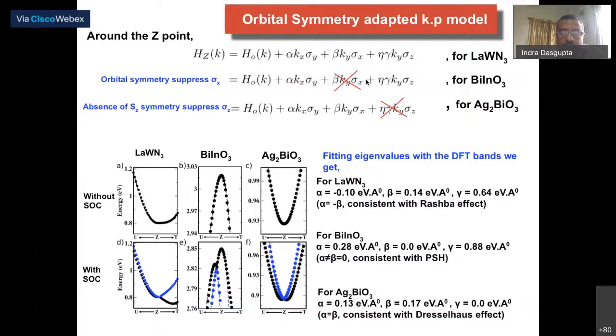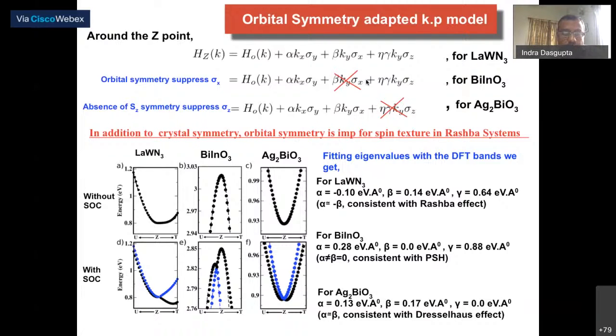So you have to include an orbital symmetry adapted k·p model. Once we do that, we have an excellent fit with our full DFT spin-orbit coupled calculations. The next step is to look at the spin textures, and we covered Rashba for LaWN3, persistent spin texture for BiInO3, and Dresselhaus spin texture for Ag2BiO3. So orbital degrees of freedom provide a kind of knob to obtain a desired spin texture in a material, which we happen to point out for the first time in the literature. What we are saying is that, in addition to crystal symmetry, orbital symmetry is important for spin textures in Rashba systems. Well, with that, I will conclude.